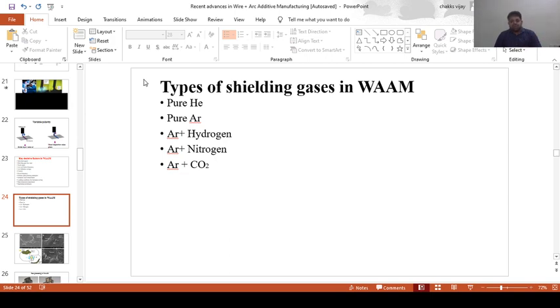As compared to nickel, nitrogen will be giving more than 10 times better austenite stabilization. Austenite phase is one of the most ductile phases, which is more preferable for obtaining very high corrosion resistance and also very high ductility. We generally go for the austenitic phase. Austenitic phase should be more, then only the material will be more ductile. If it has a lot of ferritic phase, then obviously the material will turn more brittle.